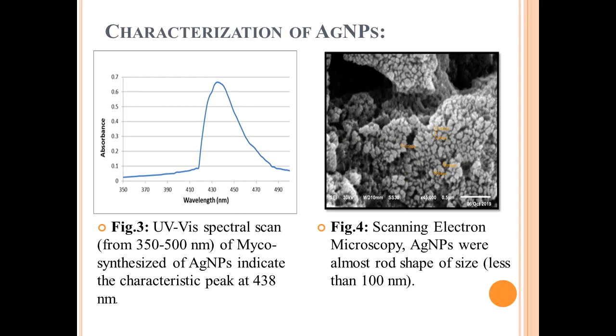Figure 3, UV spectral scan from 350 to 500 nanometers of mycosynthesized silver nanoparticles indicates a characteristic peak at 438 nanometers. Figure 4, scanning electron microscopy. Silver nanoparticles were almost rod-shaped, of size less than 100 nanometers.